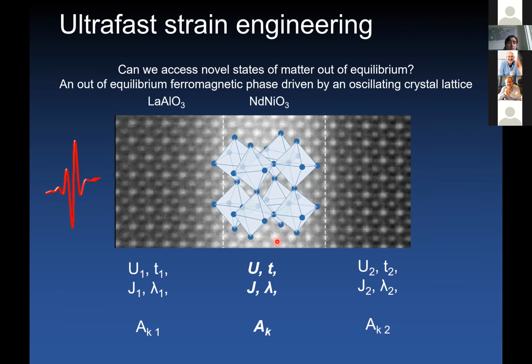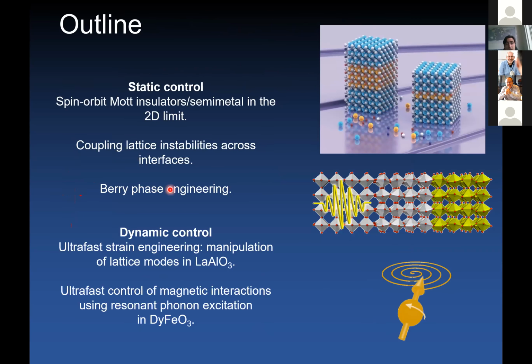And finally, depending on how much time I have left, I would like to address the question of states out of equilibrium. I would like to give you an example of a surface phenomenon in which you can drive an out-of-equilibrium ferromagnetic phase by making the atoms of your system oscillate very fast and very intensely. So this is more or less the outline. We will go from discussing static control of these interfaces towards the most cutting edge, at least for our lab, of dynamic control using resonant phonon excitations.